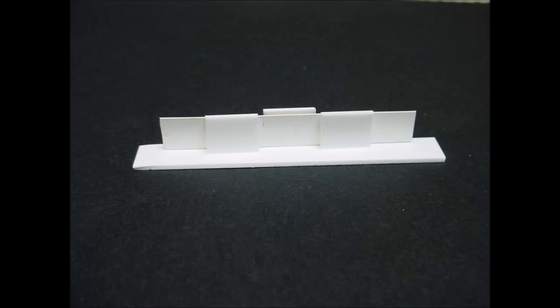Another extraordinary application of the optical dilatometer Misura LT is the measurement of the thermal expansion on extremely thin samples, so thin that they cannot withstand their own weight. They must be non-transparent though. This is the picture of a green sheet with a thickness of 100 microns. The material is high-grade alumina bonded with PVA, tape cast with the doctor blade technology.